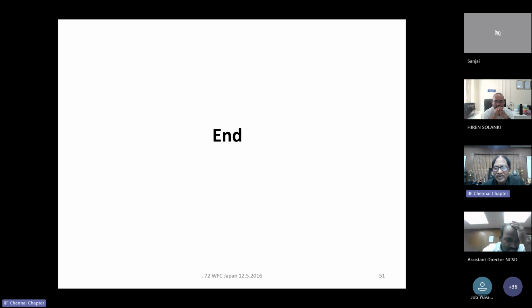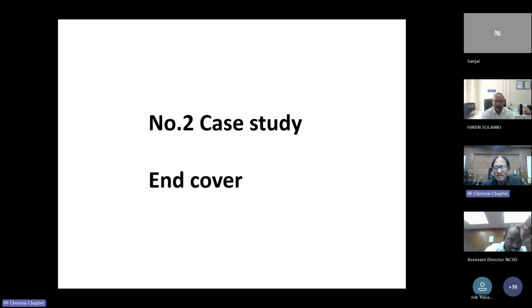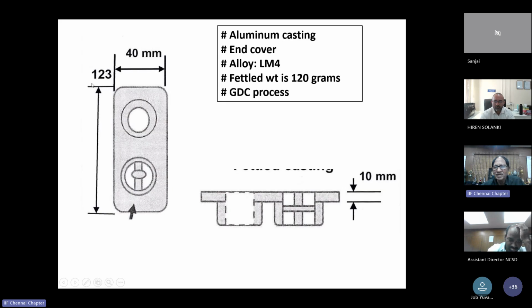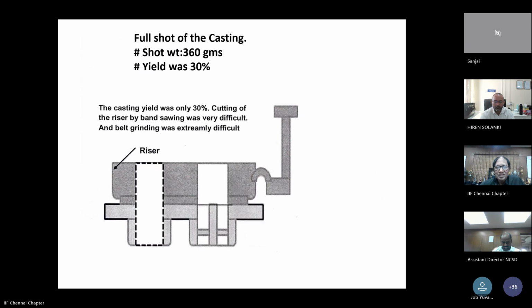Coming to second. This is the end cover, a very small casting, but it has so many problems. This is one small aluminum casting, alloy LM4. Very small casting, 123 by 40 by 10 mm with 2 bars. But the casting yield is the full casting weight. This is a small casting and a very big riser on this rectangular portion, but yield is hardly about 30%. Shot weight was 360 grams.